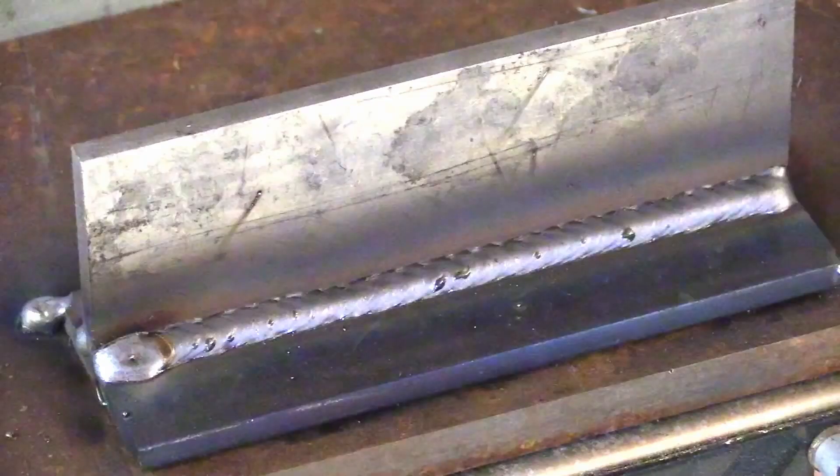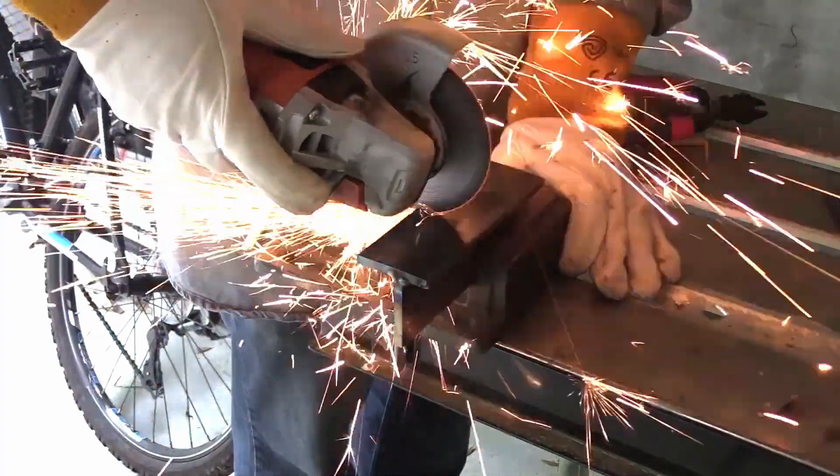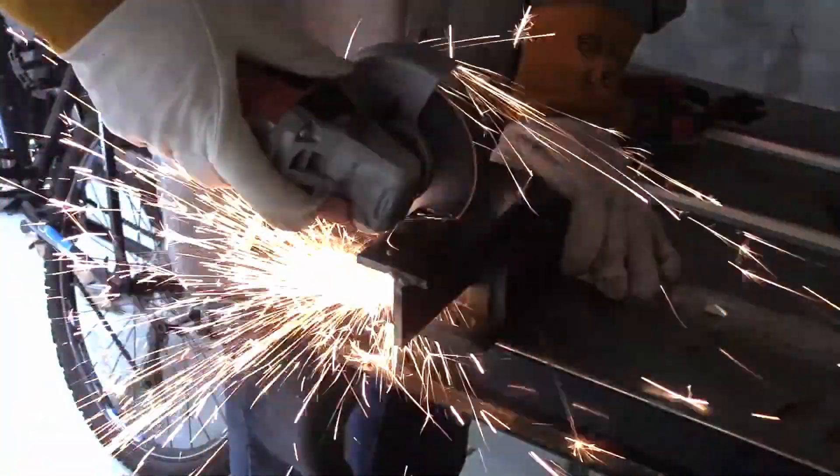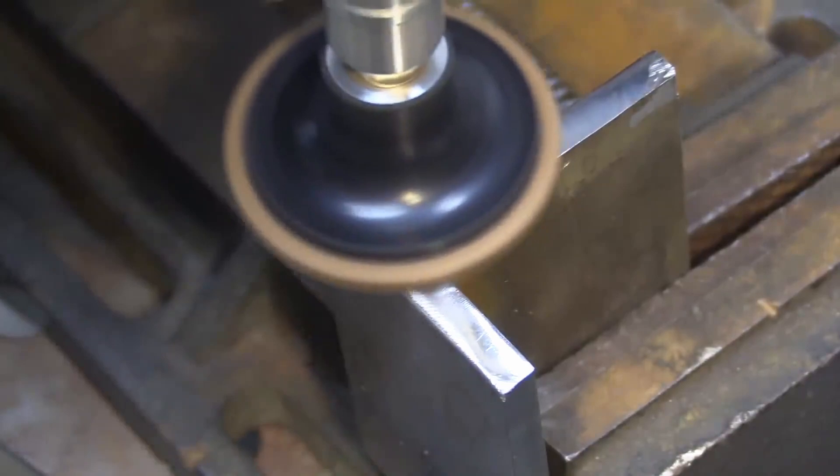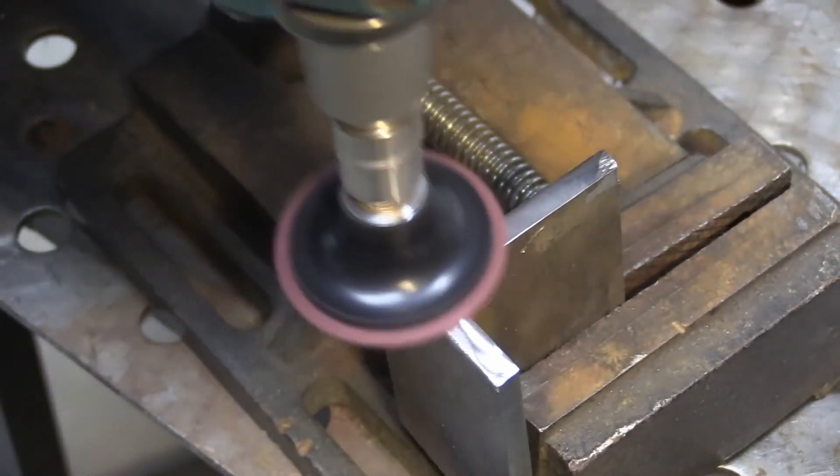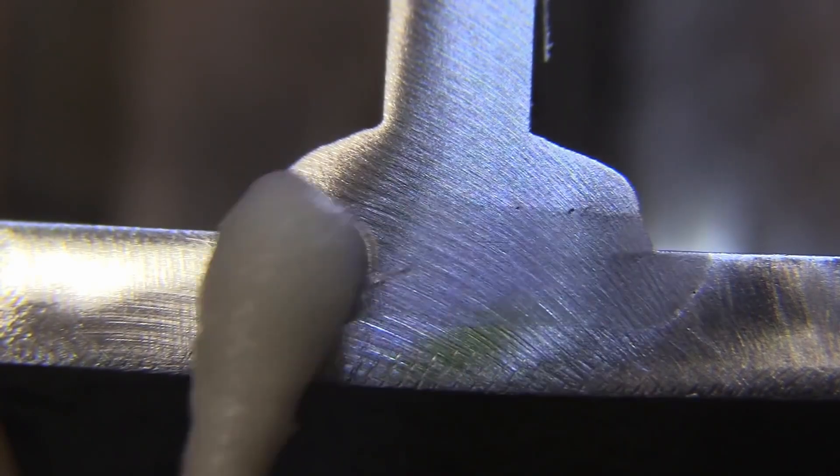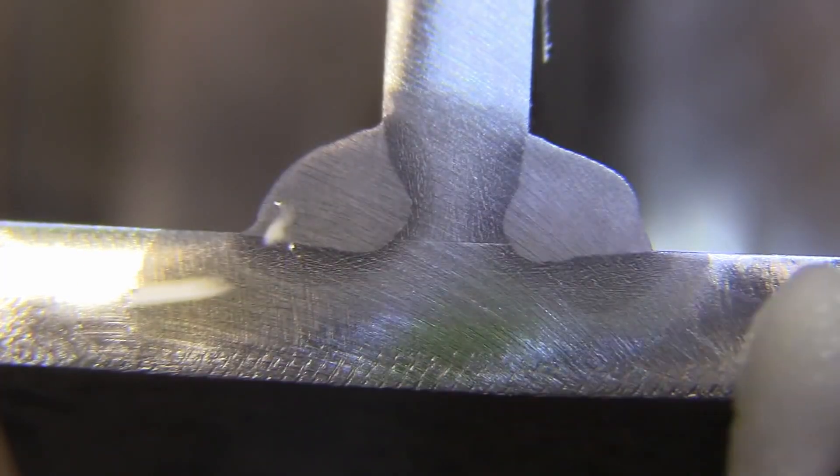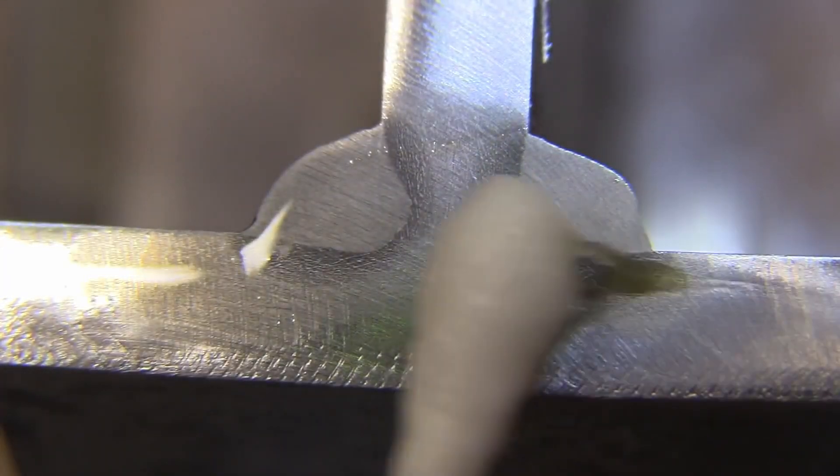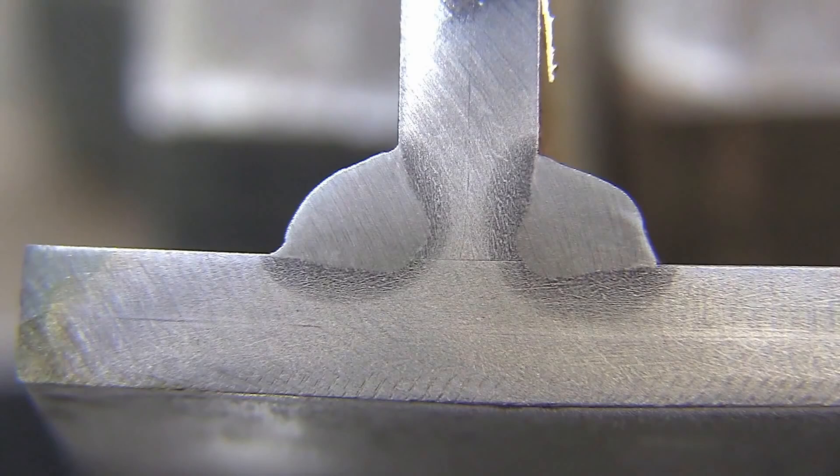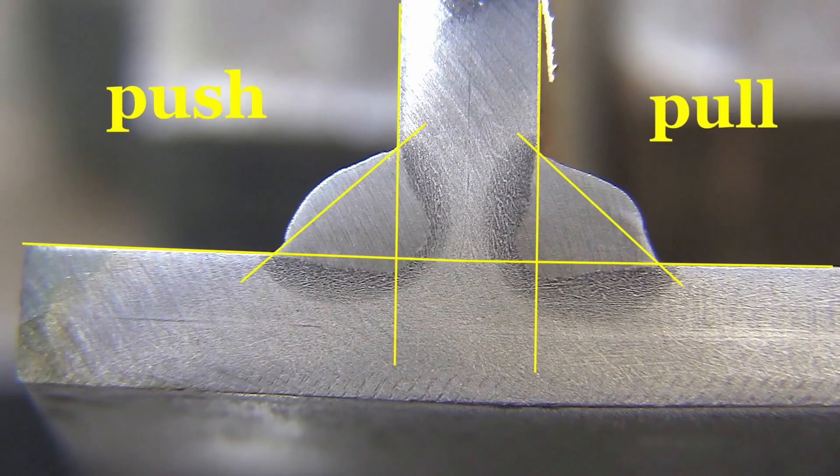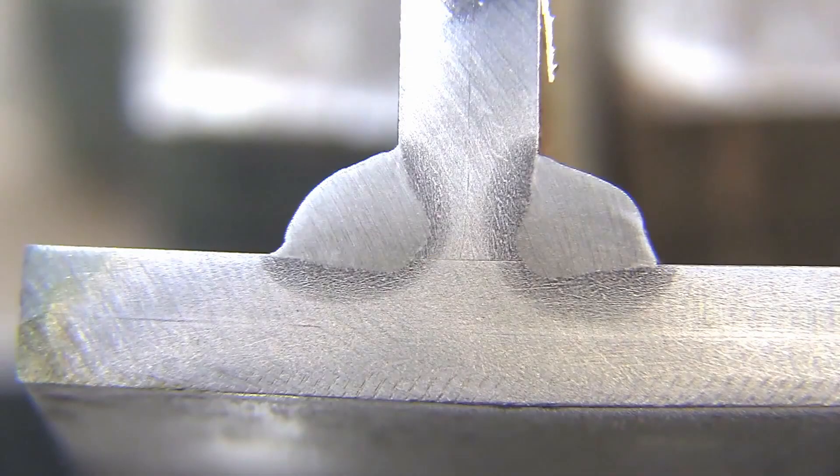Alright, the pull's done and I'll cut the pull section. There's one cutting edge in the middle here. I polished it with a brown Scotch-Brite followed by a red Scotch-Brite Roloc disc and then I've used a little bit of etch that basically is a passivation solution for stainless steel. And you can see right there there's some slight minor differences but not like night and day. We'll do a little hash mark here so you can see exactly where the penetration is and where the weld nugget is. So both of them got in there, there's minor differences.